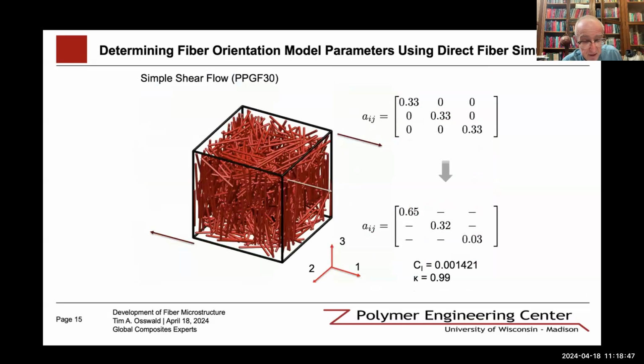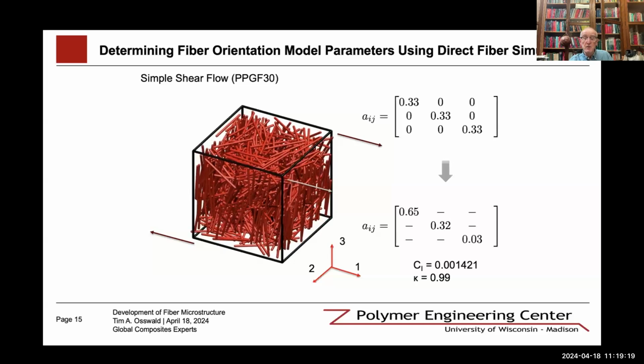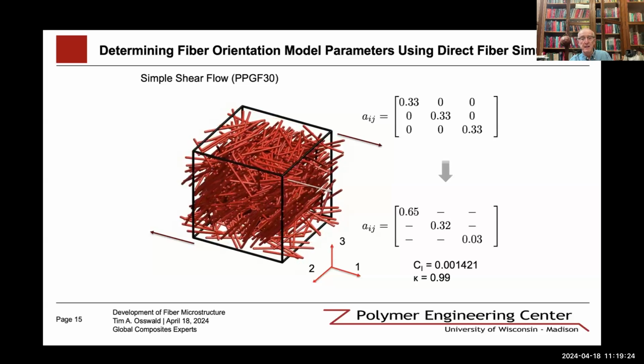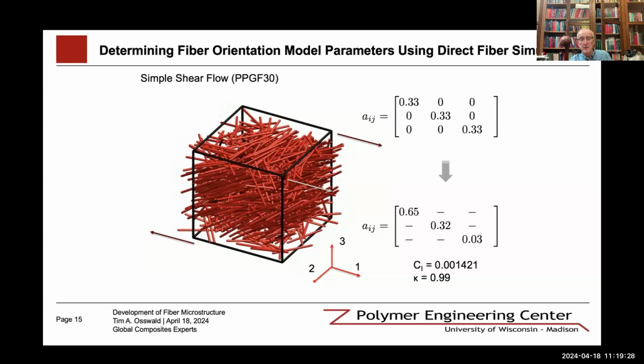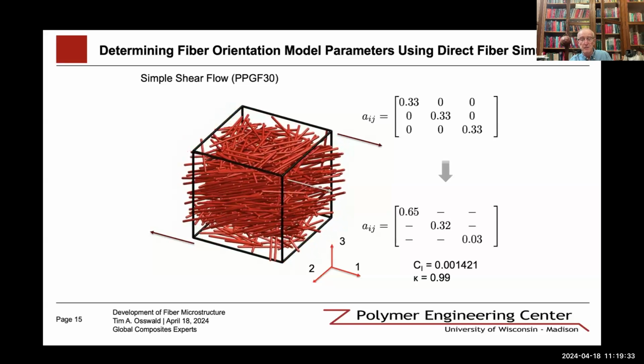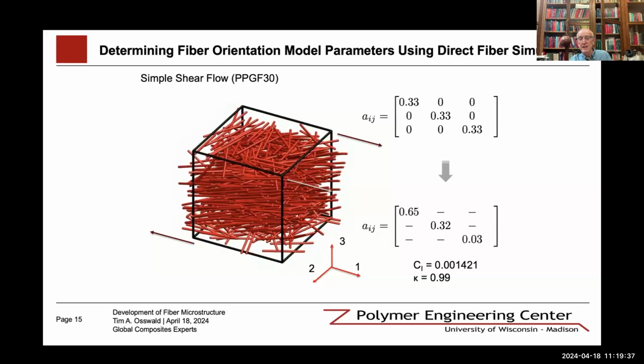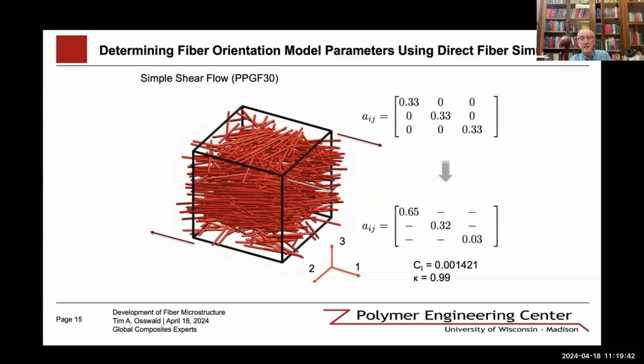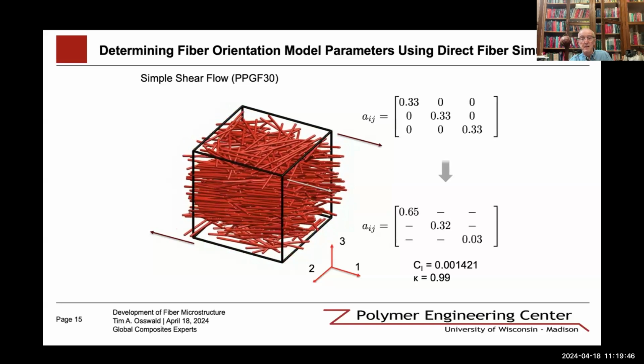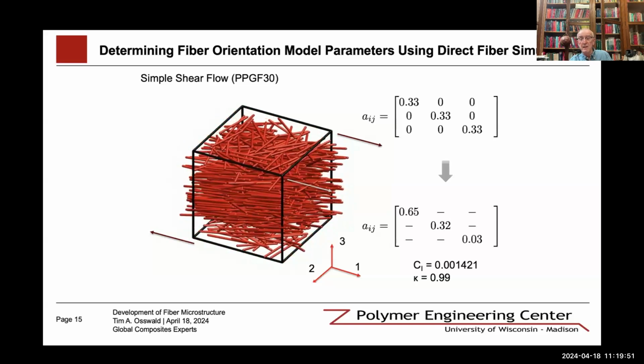And so many things that we did, working on the basis that was laid down by previous researchers, we used what we call a mechanistic model, where we model individual fibers, also called direct fiber simulation. Here we have a simple shear flow where the fibers start out randomly oriented in space. And so if we move the upper plate and the lower plate in opposite directions, and we use a boundary condition between the entrance and the exit flow, you can see the fibers starting to orient in the direction of flow. Of course, there is no orientation in the second direction, so only directions 1 and 3 are changed. In the second direction, it remains still at 0.33.